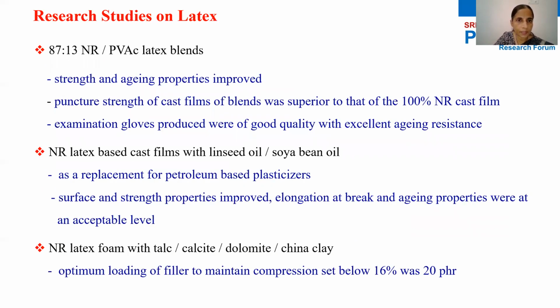Several research studies have been carried out on latex. Polyvinyl acetate, which is a stiff polymer, was blended with natural rubber latex according to a special blending technique, and cast films and gloves were produced. Strength and aging properties of the cast films and gloves were at a high level. Tear strength, tensile strength and puncture strength improved with the incorporation of polyvinyl acetate. Puncture strength of cast films of blends was superior to that of the 100% natural rubber cast film. Examination gloves produced were of good quality with excellent aging resistance.